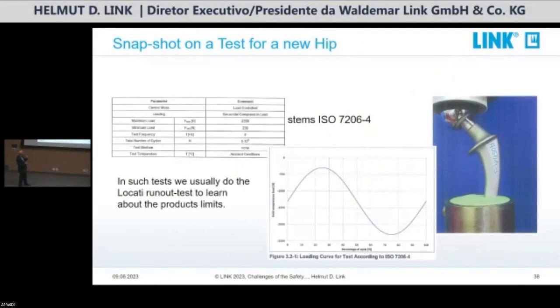For instance, when we test a new stem, we don't do only the ISO 7206-4 test, which is necessary for a hip stem, but I always want to see the so-called Locati runout test. The Locati test means we step up with our testing until the implant fractures. From that, I get the information, how strong is that? Is it only a little bit above the requirement, or is it a long way above the requirement? I want to know that.